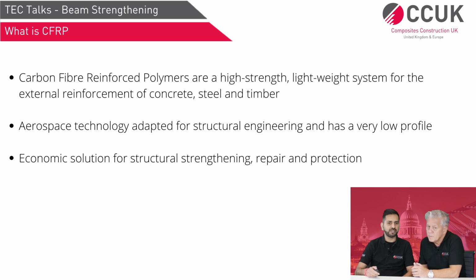And if I just give you an example in terms of numbers, carbon fibre is at least 3 to 4 times stronger than steel and at least 7 to 8 times lighter than steel. So you can see the strength to weight ratio and why people prefer to use FRP over traditional methods. And that is the reason it is becoming quite popular. The other advantage is that it can be used on concrete, steel, wrought iron, cast iron, even on timber structures. So pretty much all types of structural material can be strengthened using carbon fibre.